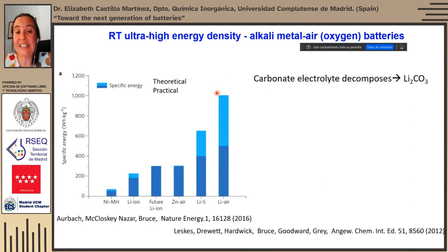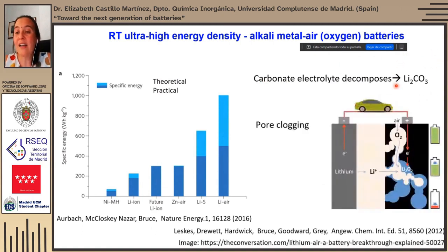Some issues related to this chemistry is that in the presence of liquid electrolyte, the previous example was with polymeric electrolyte. In the case of liquid electrolyte, there is electrolyte decomposition, and this reaction, of course, is not reversible. And also that the lithium peroxide is clogging the pores, and then when you want to discharge the battery, you want to bring the lithium peroxide back into oxygen, you have an issue because the electrons are coming from the carbon.